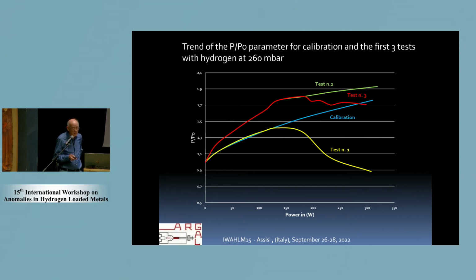The second test is the green line, and because of this big absorption during the first test, it was necessary to refill the reactor, since I wanted to make other experiments at the same pressure as the previous one. So the hydrogen was changed and refilled up to 260 millibar.